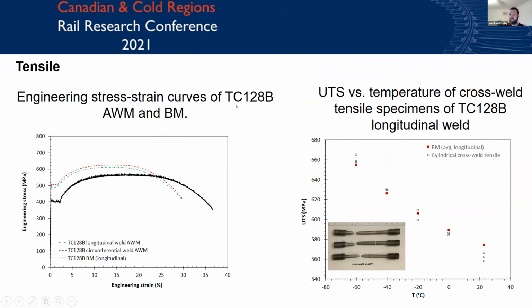So moving on to the tensile tests that we did, as I stated earlier, we did full all weld metal tests at room temperature. And these are shown on the left-hand side of your screen. The base metal in black and the longitudinal and circumferential tensile tests in red and green, respectively. You can see that the yield strength and the ultimate tensile strength of the welds are higher than the base metal. This is what we want and what we expect to see. We also see a slightly lower elongation to failure versus the base metal. Once again, all as expected.